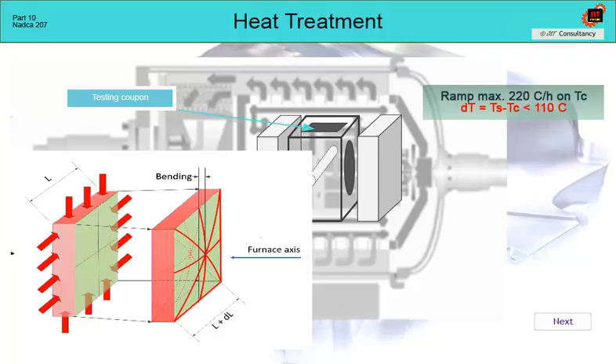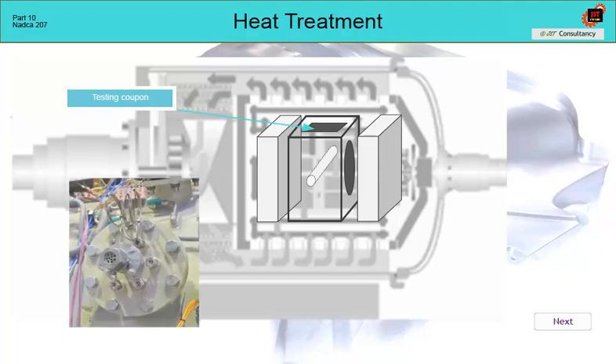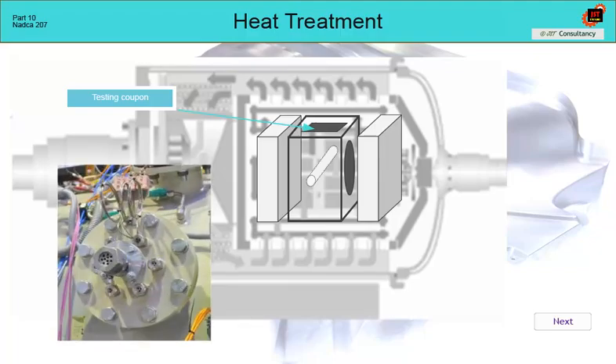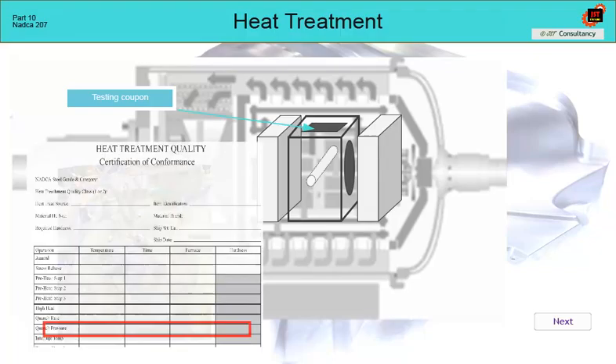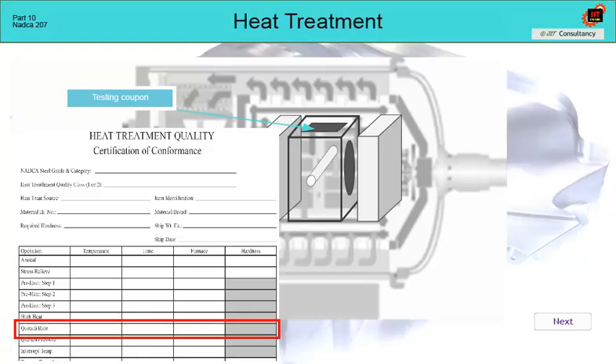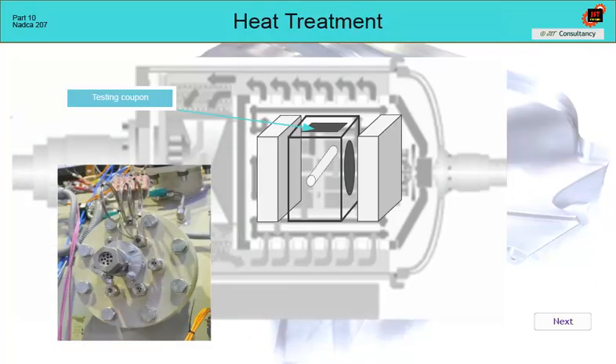Since each insert must be validated for cooling rate according to NADCA 207, the process must include a record of the thermocouple location, for example in the form of a photograph, as well as a record of the process parameters, especially TS. The read cooling rate is then stated in the processing report. If we are only quenching one insert, this is not a problem. However, if we are quenching several inserts in one batch, we must choose a solution.